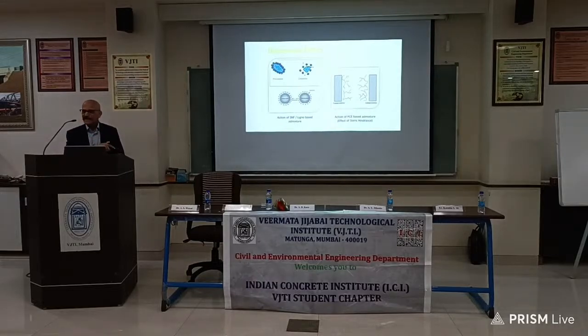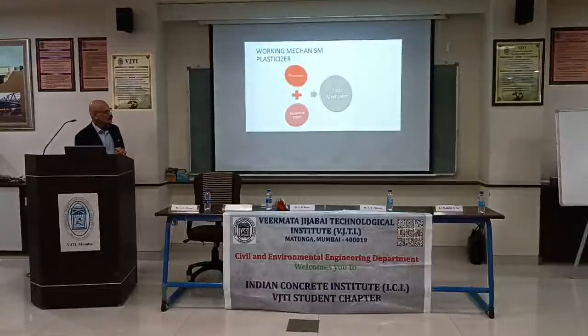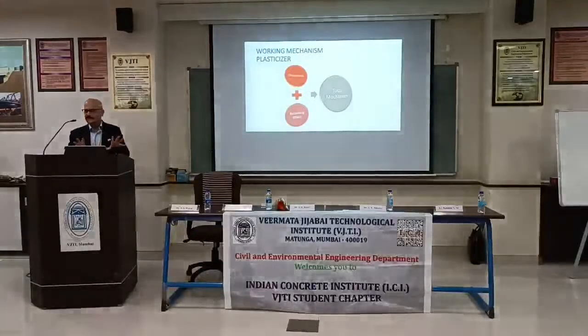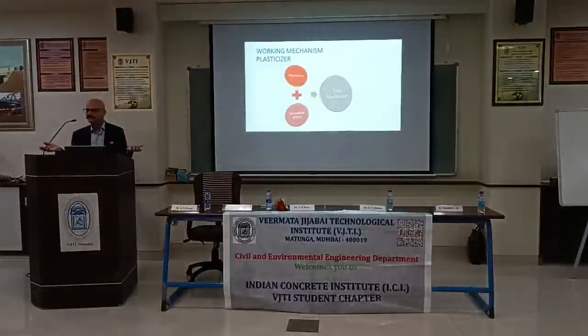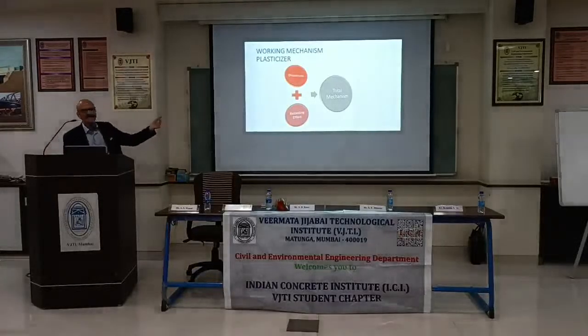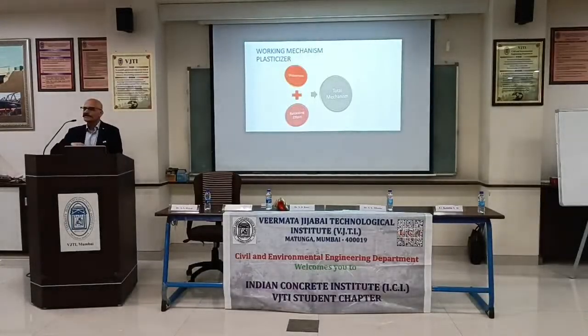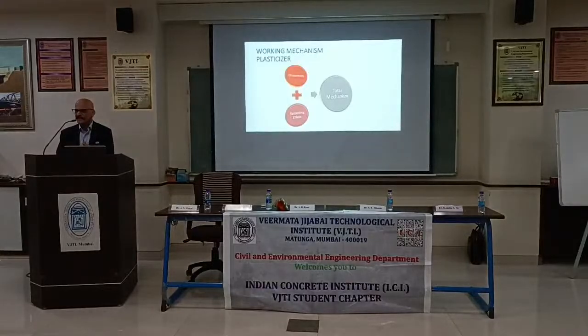So this is one mechanism, that there is a repulsion. There is one more mechanism which is coming. Now, on the cement particle, they act like superplasticizer. One is dispersion, so you get flow to the mix. And second is a retarding effect, because the hydration stops for a while. That hydration can be stopped for 2 hours, 3 hours, 4 hours.